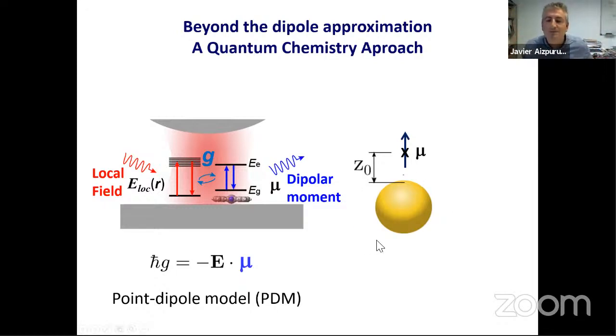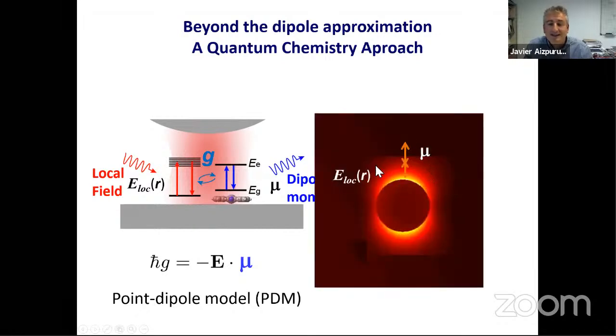But when it comes to plasmonic cavities, or even plasmonic pico cavities, where we are localizing the field in a few atoms, so in a few nanometers, the point dipole here, this mu that I put here with this arrow, is located somewhere in the middle of this strongly inhomogeneous plasmonic field. The plasmonic resonator, the near field, the local field associated to the plasmonic resonator is extremely inhomogeneous. So to put a molecule, which is of the order of 1 nanometer or 2 nanometers, in a field that decays in less than 1 nanometer, is again an approximation. And here you certainly have this approximation of E dot r, which works in principle, but not for these evanescent waves, right?